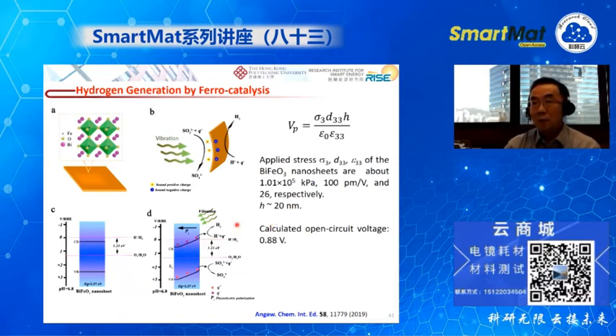So we believe that it is due to the piezoelectric voltage generated across the two sides of the nanosheet. So when we apply a resonance to the material, when we deform the material, we get a piezoelectric voltage being generated across the nanosheet, and the piezoelectric voltage will tilt the band. It makes the energy band structure tilted, and therefore,